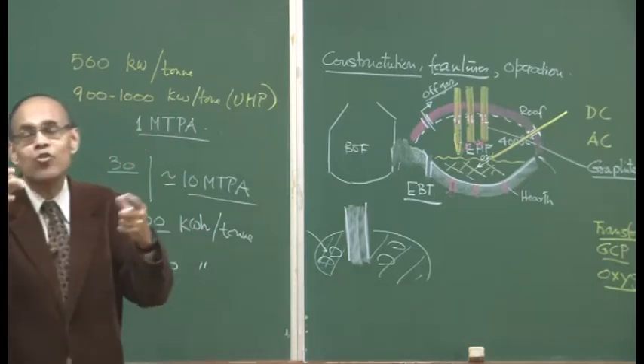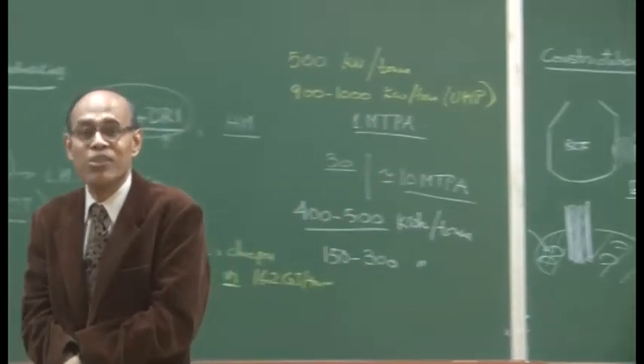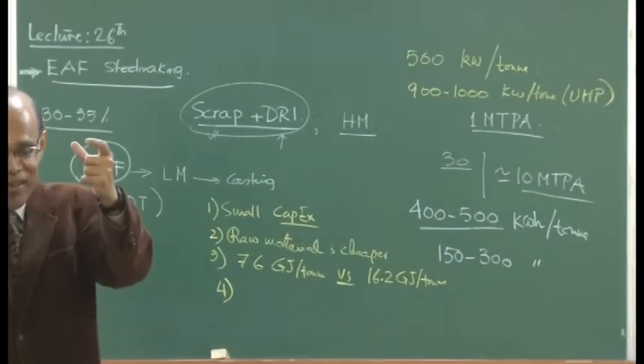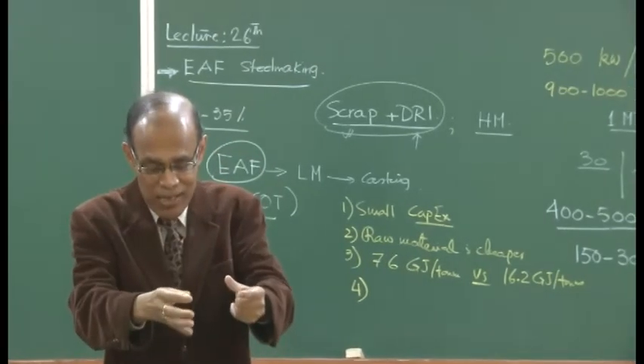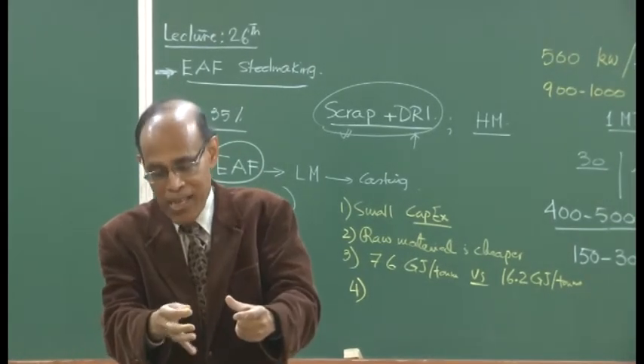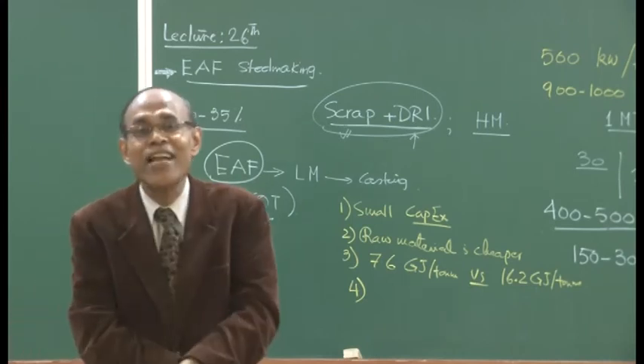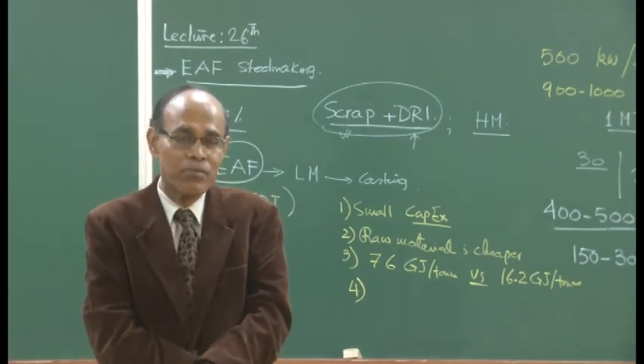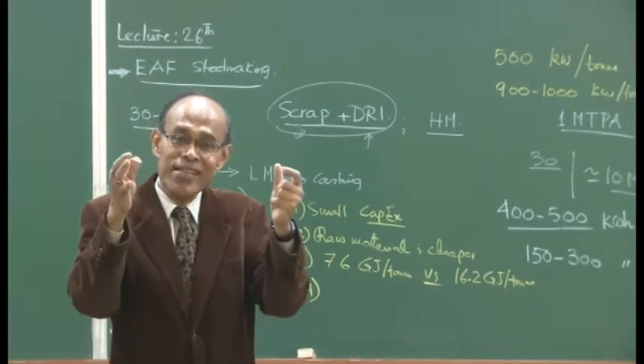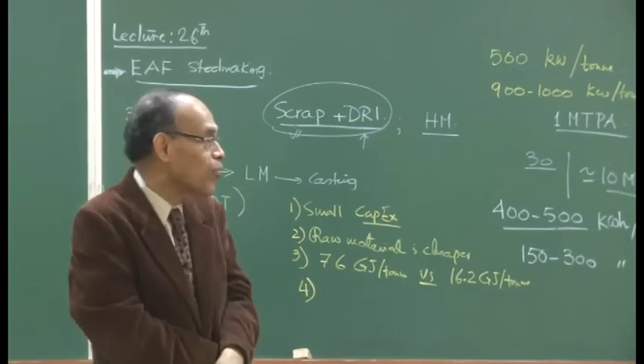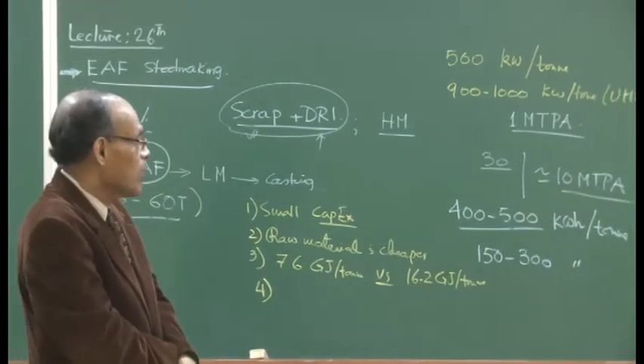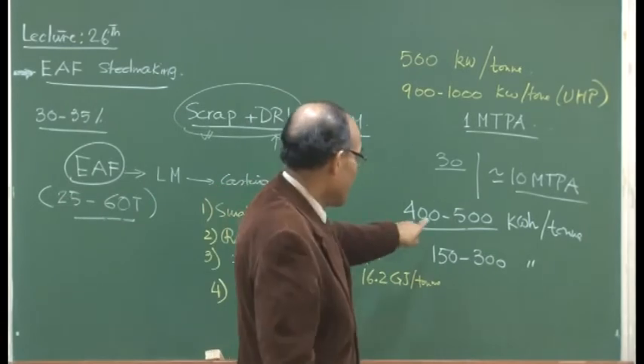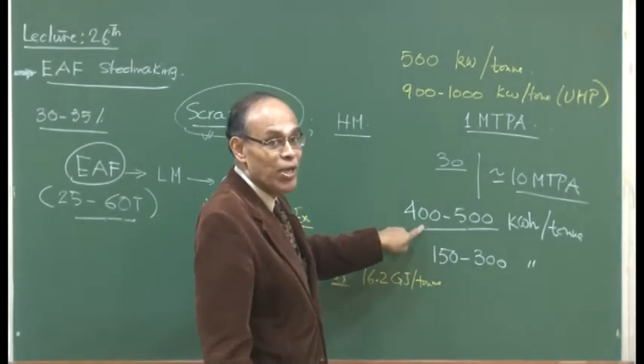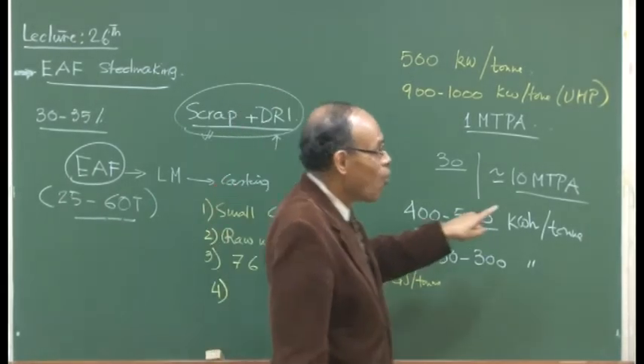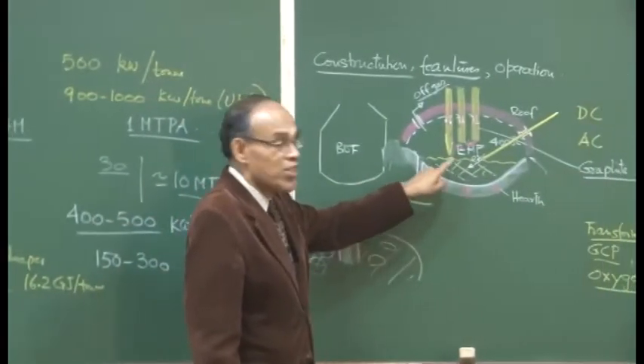just like the way I taught you during the Midrex process, that you have the Midrex pre-reduced pellets which are produced from the Midrex furnace, and then you charge it directly into the steel making furnace, so that the sensible heat which is contained in those pre-reduced pellets can be utilized, and you can significantly bring down this energy requirement if you use hot DRI or hot scrap into the system.